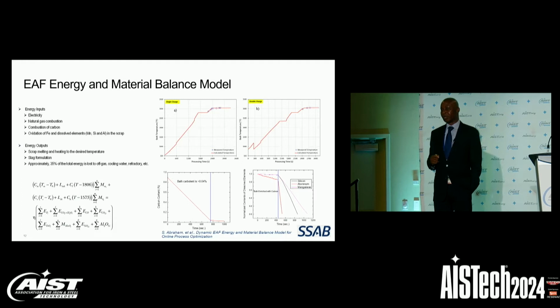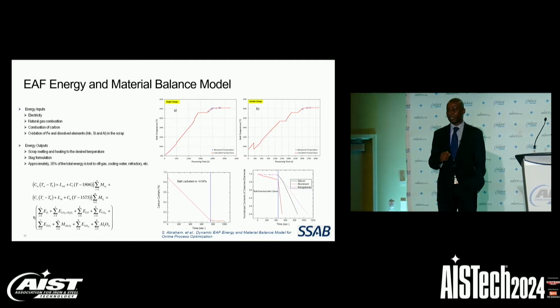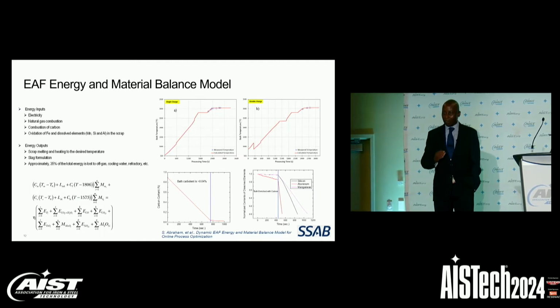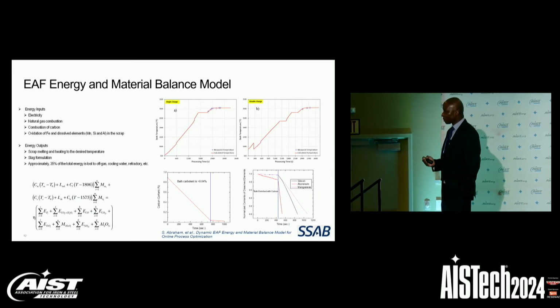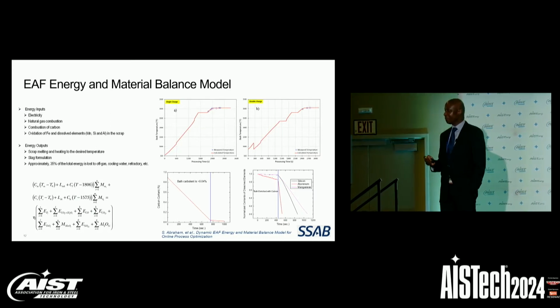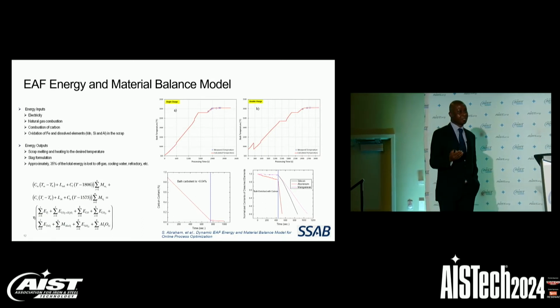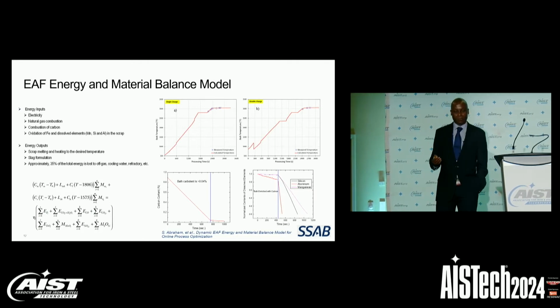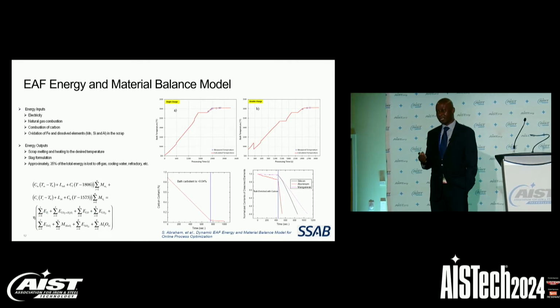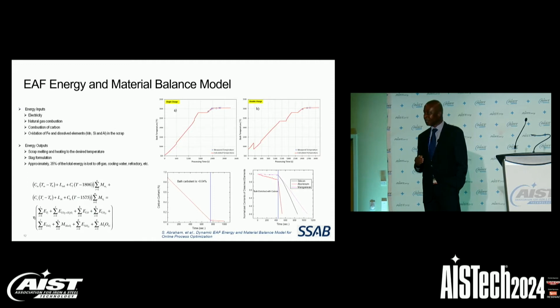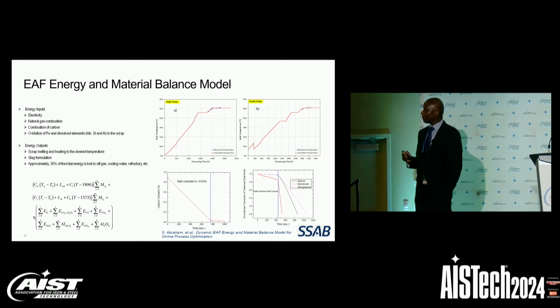The process is multiphysics, involving chemical reactions in different phases that are in thermodynamic pseudo-equilibrium with each other. All of this creates an environment that is harsh, aggressive, and corrosive. Hence, it is impossible to continuously measure the temperature of the bath during the scrap melting. A decision on when to make an intermittent temperature measurement is based on the judgment and the experience of the operators. Hence, this can lead to inefficiency in the process.